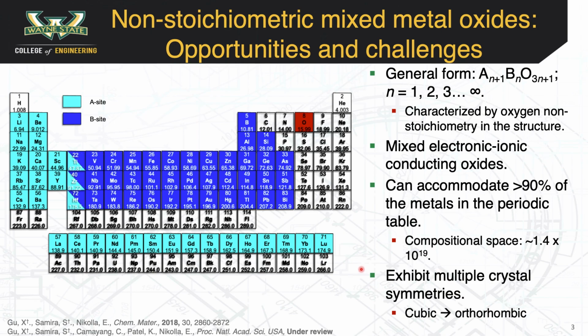In addition, these oxides can exhibit multiple crystal symmetries, stemming all the way from highly symmetric cubic structure to tetragonal to rhombohedral and the less symmetric orthorhombic structure. This enormous phase space in terms of the compositional space and the crystal structure can affect its electrocatalytic activity. Therefore, in order to identify optimal electrocatalysts for targeted electrochemical reactions, there's a need to develop predictive tools that can determine an optimal electrocatalyst for a targeted electrochemical reaction.